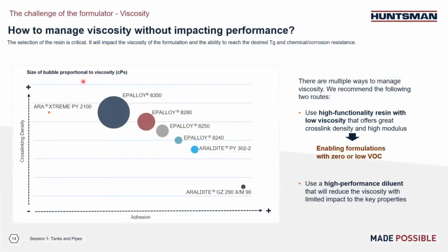So in this slide, we're listing several epoxy resins here. And you can see the y-axis is cross-linking density, the x-axis is adhesion, and the size of the bubble is proportional to the viscosity. So if we look at this Araldite GZ290 X/M90 epoxy resin, it has a lower viscosity and very good adhesion. It is a fatty acid modified BPA type epoxy resin, so it also gives very good flexibility. So it's very good for corrosion resistance. So for anti-corrosive primer or DTM primer, this will be a good choice.